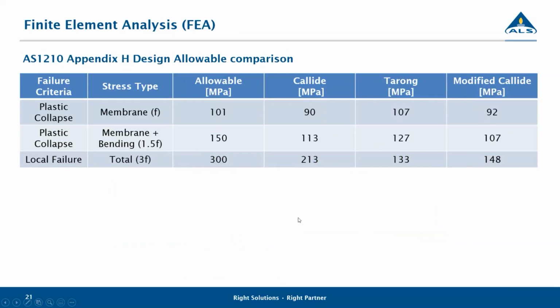Here is just a comparison of the stresses for the 3 designs. You've got the Callide, Tarong, and modified Callide design, and you've got the allowables for plastic collapse against membrane, and then plastic collapse against membrane plus bending, and then local failure for peak stresses. But the interesting thing is that if you look at the Callide versus Tarong design, the actual membrane stresses on the Tarong side are higher, and the membrane plus bending as well. And that's probably because that bracket ties into the bend itself and doesn't run past the bend. But the big difference was in the peak stresses.